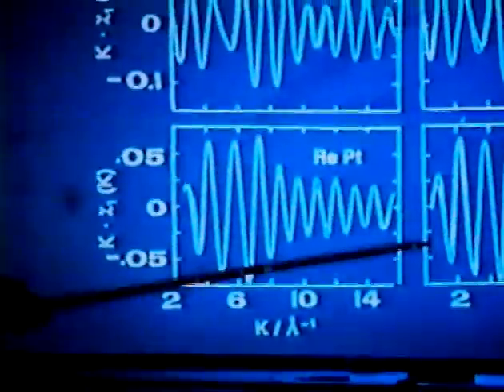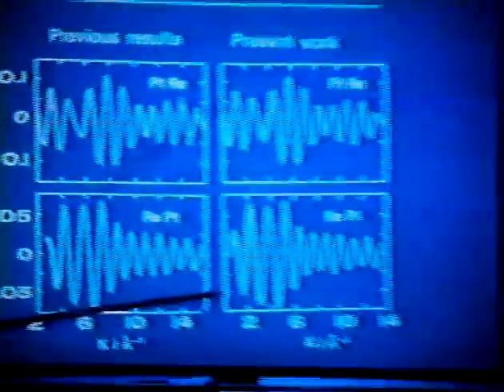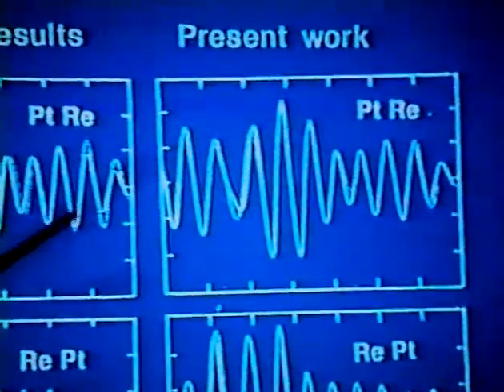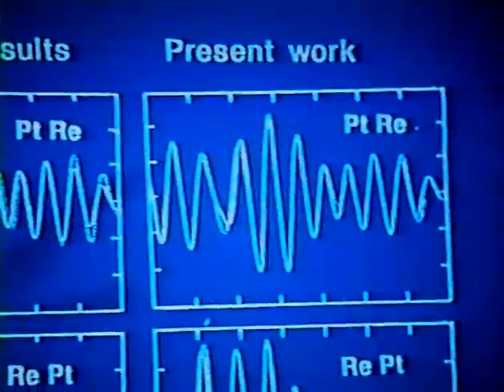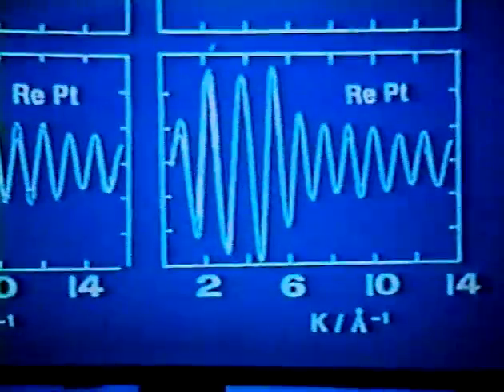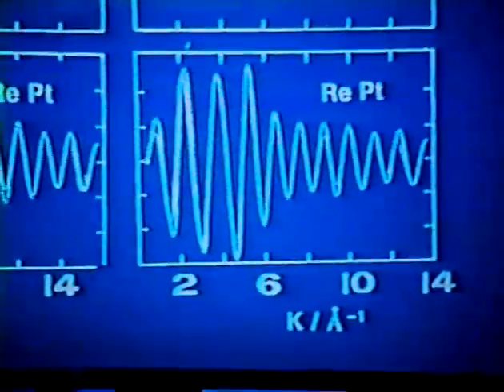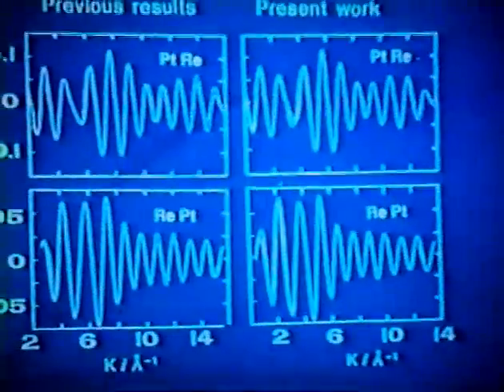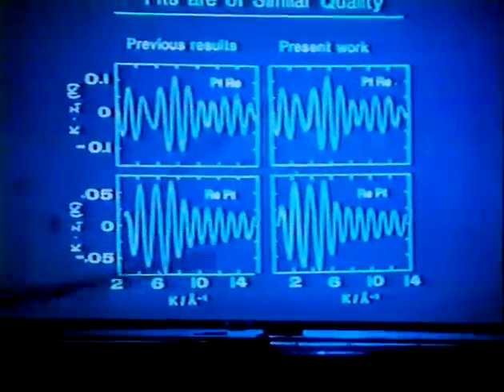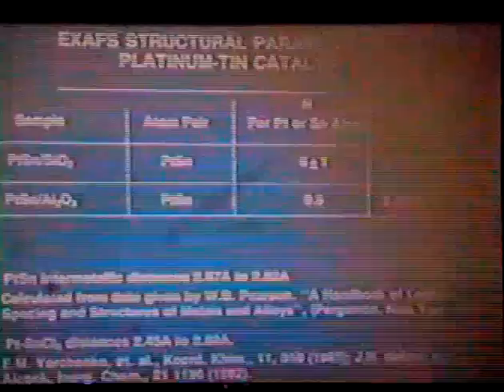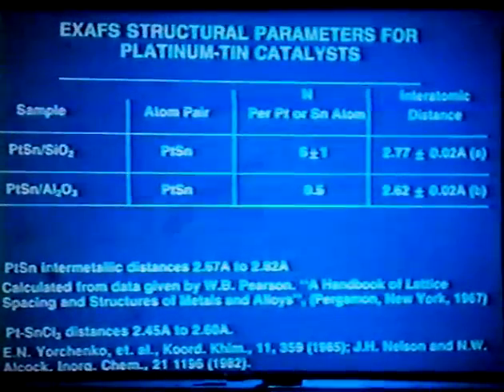Now, in our present work, instead of 13, we had 9 adjustable parameters for analyzing both spectra simultaneously. It's not a coincidence that the fits are just as good as they were previously. That's because, as I said, some of the variables were degenerate. So what we've shown is that using a smaller number of variables, you get more data out of the system, and you get equally good, qualitatively, fits. Next slide.